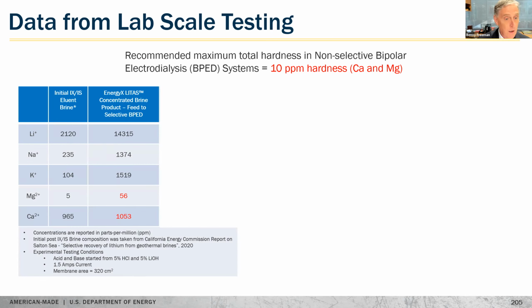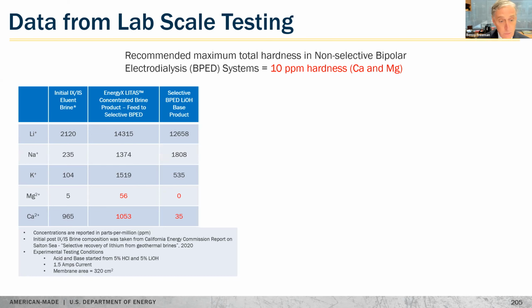This is a stream that's coming out of our Litus system, and so it's been concentrated, as you can see, 7x in lithium, and there's also some separation going on here as well. And again, we've spiked the magnesium in this one. Next slide. Now coming out of the bipolar electrodialysis cell, we have virtually all of the lithium that we put into the process, and you can see that we really brought down the magnesium and calcium levels.